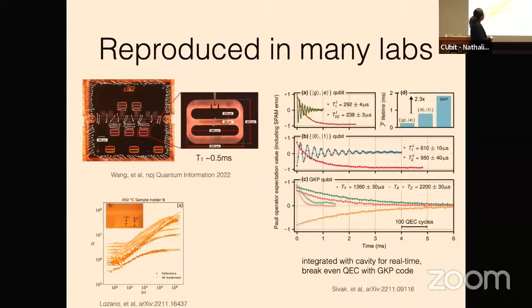And I should say that since then, this essential result has been reproduced in many labs. So there's a group in the Beijing Academy of Sciences that has gotten T1s up to 0.5 millisecond or quality factors up to around 10 million. The IMEC group has been making tantalum on silicon resonators where they're able to see Qs of something like 5 million. And then most recently, Michel Devoret at Yale has used a tantalum qubit in their GKP code experiment to get real-time break-even quantum error correction. And there were many advances that led to this result, but at least one of them was that they switched to a tantalum qubit with a T1 of almost 300 microseconds.